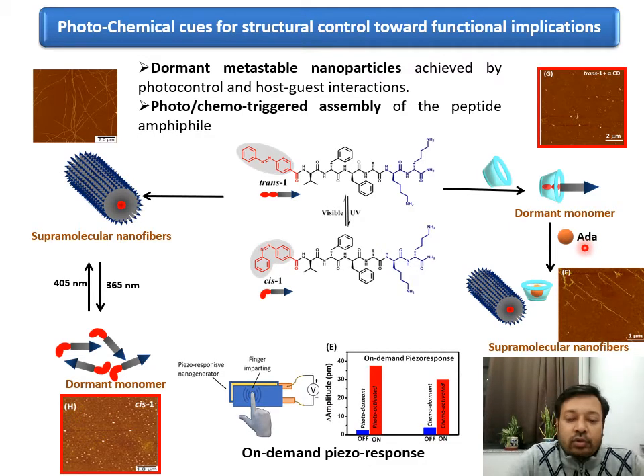Now, having done so, we also looked into the functional property of such peptide amphiphiles. Because of these multiple amide bonds, they have very nice spontaneous polarization, which can be utilized for looking at the piezo response. And we have seen, if you have this chemo and photo controlled self assembly and disassembly, you can also control very nicely the piezoelectric response of this material, which is certainly a very interesting aspect.